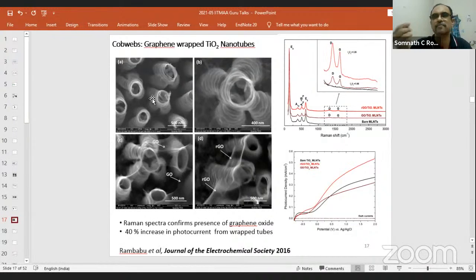We had some hint from a previous paper, and we changed the chemistry of that. And we got these beautifully separated nanostructures, which are no more very compact. Now we had plenty of space in between the nanotubes. And in doing that, we also got a strange morphology, multi-leg nanotubes, but that is not the primary focus here. But as you can see, each nanotube, which is grown from the titanium foil, is well separated.